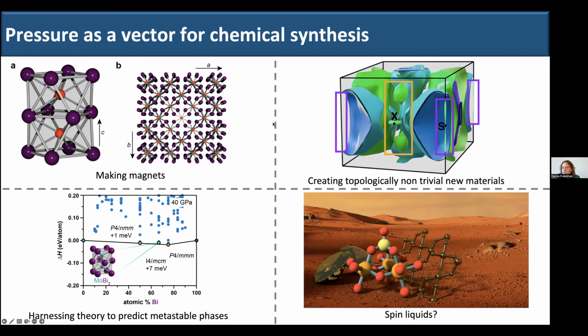As you can potentially see by the graphic in the lower quadrant, we're working on predicting the stability of these phases, and now this is something that we can do in-house. Even for a non-theoretical person, it's not that hard to predict what compounds will form. But what happens when you release the pressure, once you're under kinetic control, that's the hard part. So about 50% of the compounds persist, and it really depends on the bonding. We have some hypotheses about the structural changes of bismuth, and the bismuth 3 phase in particular, as it relates to decomposition. But I don't think there is a good general rule that I would apply.